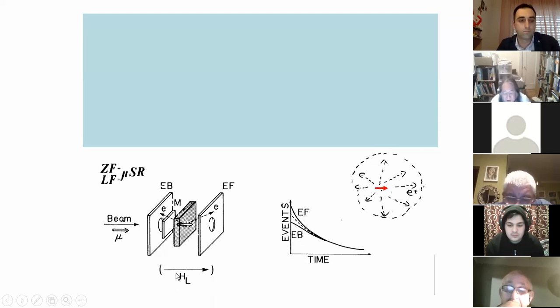On the other hand, by some mechanism of solid state physics or whatever reason, if the spin polarization is destroyed and lost, then this ratio of forward and backward counters would become 1-to-1 after normalizing for some solid angle factors. And so just by measuring the ratio of forward and backward counters, we can record the time evolution of muon spin, how this spin is, if it's stable in the material or if its polarization is decayed as a function of time. And this can be done nicely in zero field. Okay, you don't have to apply an external magnetic field. This is radioactive decay of the particle carrying out the spin information. And so we can get the spin information just in zero field.